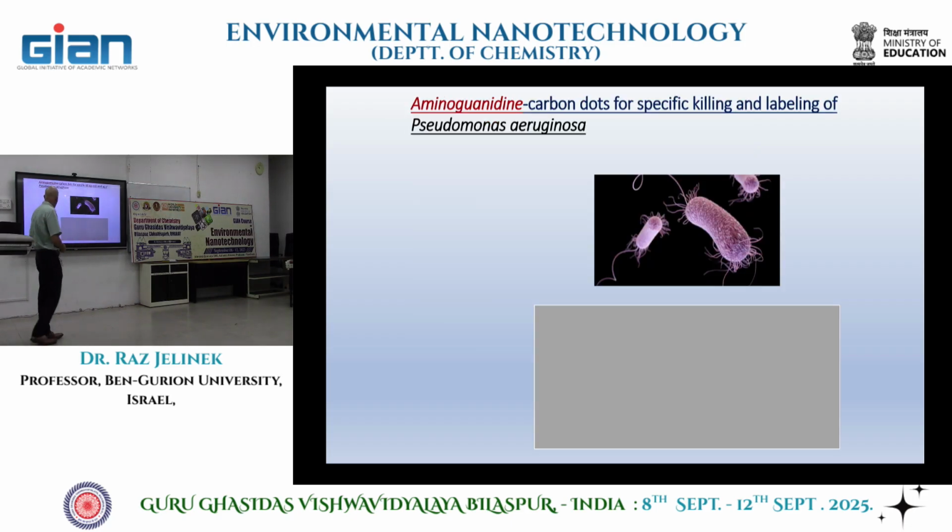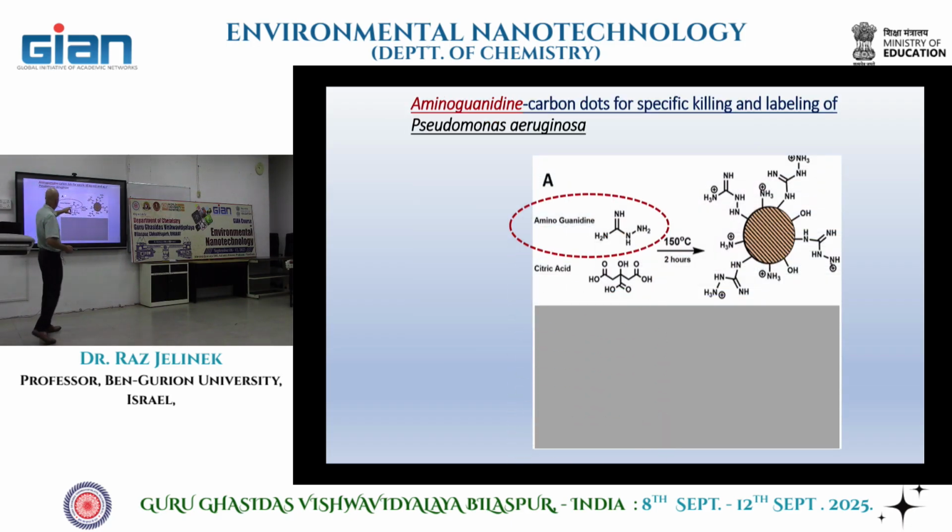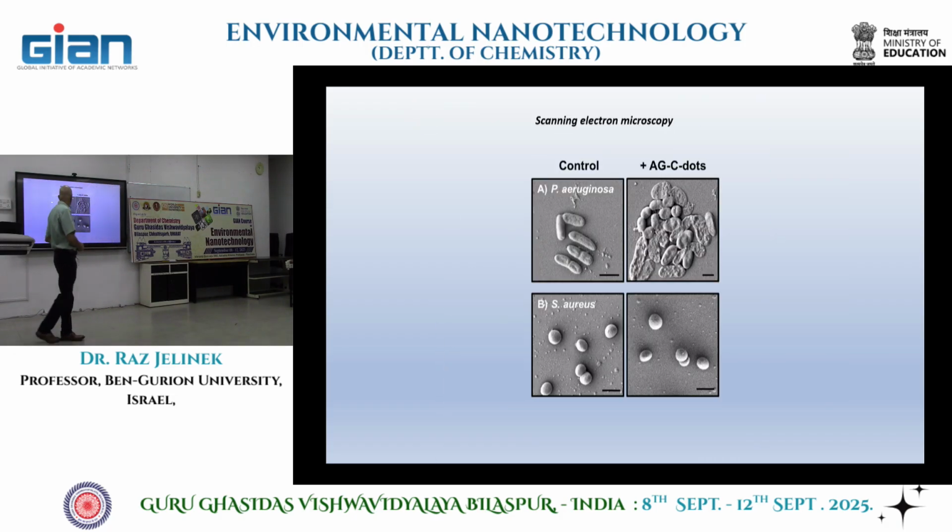So, carbon dots with the guanidine head group cannot bind to the Staphylococcus surface. So when we mix Staphylococcus bacteria with the carbon dots, nothing happens. Because the carbon dots cannot bind to the surface of this bacteria.